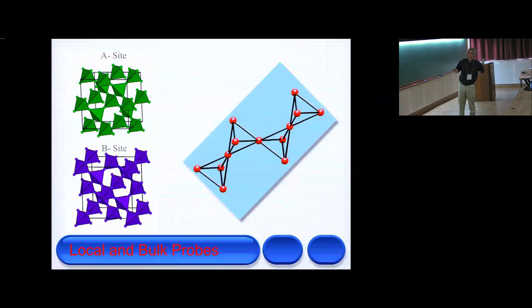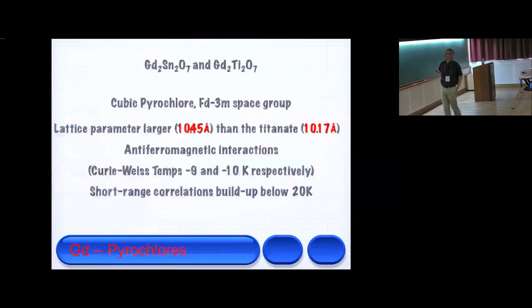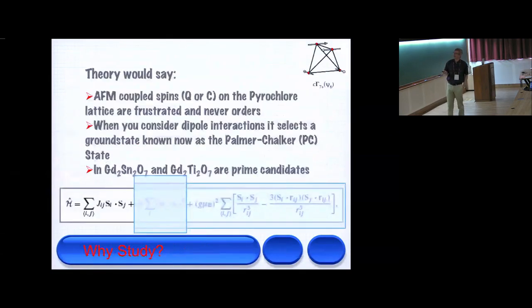And actually I don't have it in this slide, but if this was the rare earth A site, in the middle of every tetrahedron, there's an oxygen. And this is critical to pyrochlore physics, especially the rare earth pyrochlores, because that basically means that the spin on this, say this ball here, with an oxygen here and here, will either, because of crystal fields, want to point directly at the oxygen or perpendicular to it. So you find that most of our samples are either Ising-like antiferromagnets, as I'll show, or XY-like, where the spins are in this plane perpendicular to the two oxygens. It's Ising because it either points in or out of the tetrahedron. So that was the math.